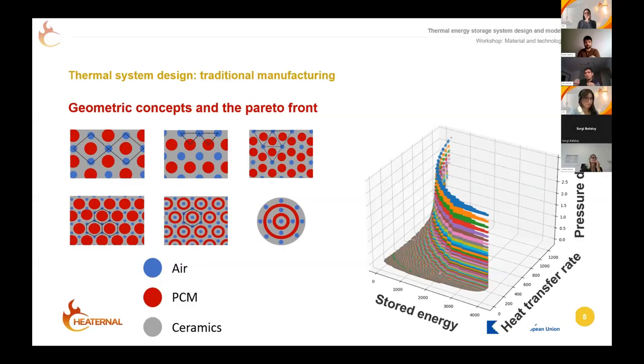fronts. So the optimal points where, for example, your stored energy is, you can't increase your stored energy anymore without increasing pressure drop or decreasing heat transfer rate. And all of these points form a front. If you compare all the fronts for these different geometries, you find that that ring design actually obtains, in the regions we're investigating, the best performance. So we went for those rings.